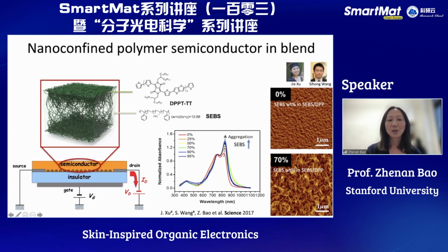But very importantly, we can't just mix some kind of nanostructure with an insulator and try to form a good conductive film, because the nanostructures may not be well interconnected. So we have to figure out a way to induce nanostructures to preform already in solution. And we found that adding these SEBS type of polymer can induce aggregation formation. From the UV-vis, we can see the aggregation peak increase as we increase the amount of SEBS,